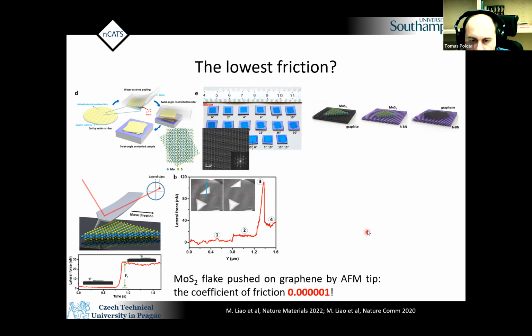So the friction here is close to zero. So all friction we measured is because of the edges. And when we look for graphene, we got the opposite thing, if you look at graphene on graphene. So we have the edge pinning strength, which increased with the domain perimeter. So basically this was dominated by the edges, the graphene sliding, and not by the area in between.